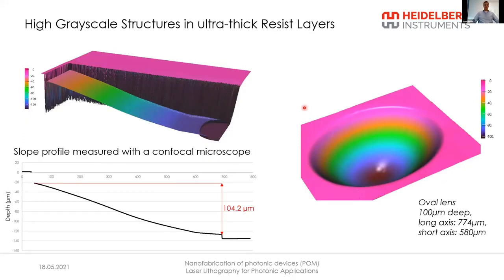However, we are always working to improve things, and this is a very new example of something that we're testing right now. Together with a manufacturer of photoresists, we try to find a resist that can expose to depths of up to 100 micron or possibly more. So this is a very first test result. The resist was coated to about a 140 micron thickness, and we exposed the slope that's not fully optimized. So it's basically a first test, but you can see that we already have a usable range of about 100 micron in this case. And this was the first test of an oval lens that we did. It's also quite promising. So that's something we're working on at the moment.